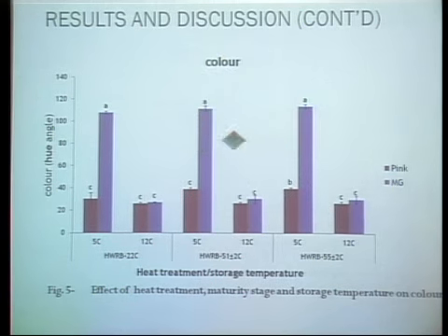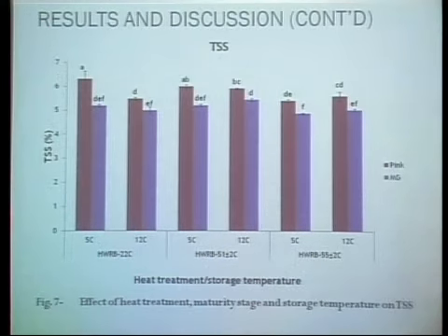So we can say that these two heat treatments, that is 51 and 55, significantly inhibited the color, and then it was much more pronounced at 55 than at 51 in the color.